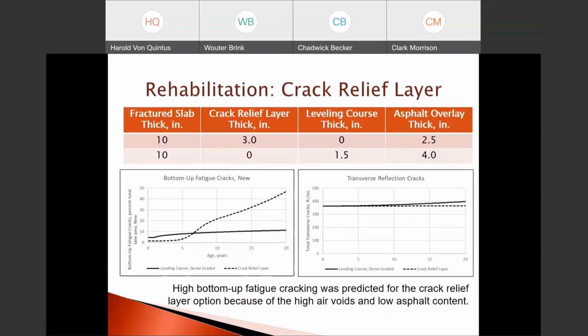So now this shows the comparisons of these two strategies. The graph on the left is bottom-up fatigue cracks. The dashed line is the crack relief layer. The solid line is the leveling course, using the leveling layer with dense graded materials, no crack relief layer. The graph on the right shows the predicted transverse reflection cracking. The solid line is the dense graded material. The dashed line is the strategy using a crack relief layer.